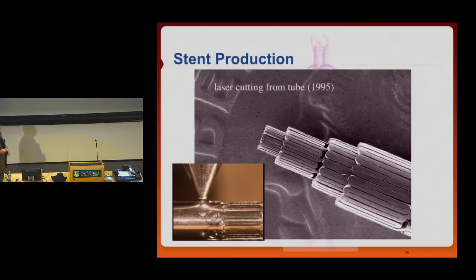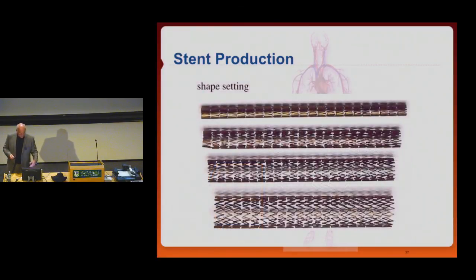The whole development of the applications coincides with the development of the material itself. For example, before 95, we did not have tubing, so you couldn't make a stent out of tubing. You would have to do braided wire or something like that. But we developed tube drawing around 1995, and now tubes are available from several vendors. And we also developed the laser cutting of this stuff. And now with the tubes, you can laser cut, and you can make the most complicated shapes.